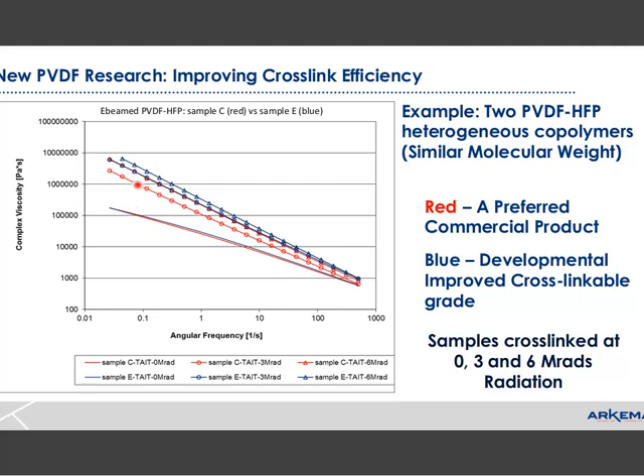I'll be comparing the red line here with the blue line right here. What we see is that the blue line is higher, which means that it has a higher viscosity and that it cross-linked more efficiently at 3 megarads. And then at 6 megarads, where there's a triangle, you can't see it, but it's underneath for the red, and a triangle for the blue, you can see that at 6 megarads, the new copolymer cross-links a little bit better. And a nice, easy way to describe this, though, is looking at the overlap here.